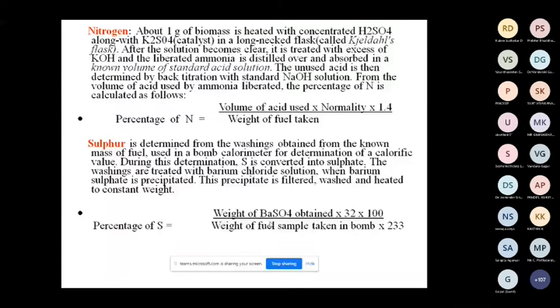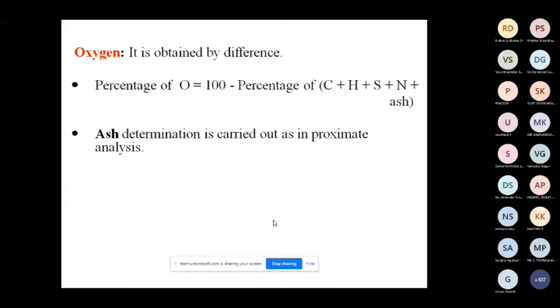Oxygen is obtained by difference: percentage of oxygen is equal to 100 minus percentage of carbon, hydrogen, sulfur, nitrogen plus ash. As we do in the proximate analysis, from that you can calculate whatever carbon, hydrogen, nitrogen, sulfur, oxygen is in the fuel. That is called ultimate analysis of the fuel. These are all conventional analyses. If you do by whatever method I told, carbon, hydrogen, nitrogen, I think it will take minimum 1 or 2 days for one fuel. Doing the Kjeldahl method, then sulfur method, carbon, hydrogen, it will take maximum 2 days per analysis.